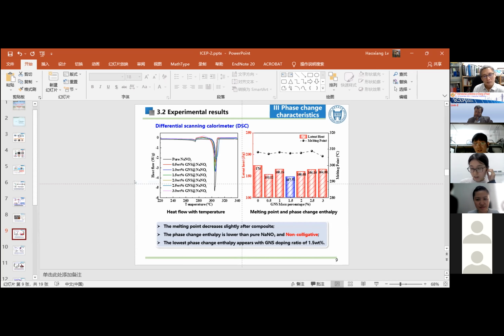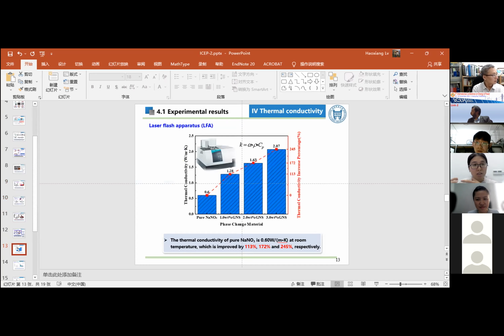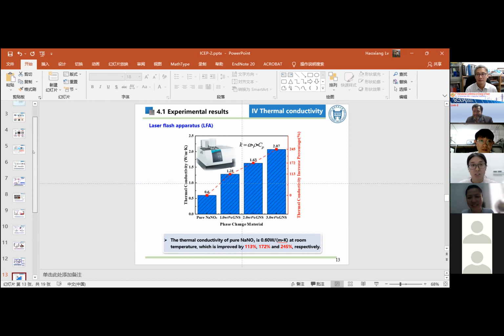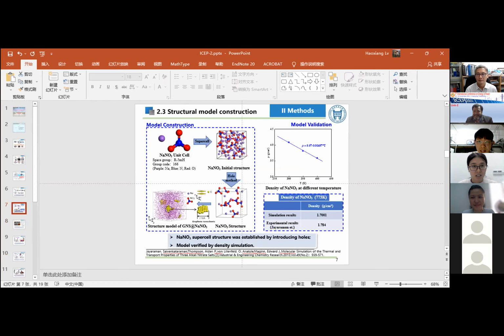And then I'm wondering about the thermal conductivity you've mentioned in your material. Does this thermal conductivity have something to do with the direction of the material? I mean, is it isotropic or anisotropic? The composite is uniform in all directions, because the GNS is dispersed in the sodium nitrate randomly, so we can ignore the influence of direction. Okay, thank you.